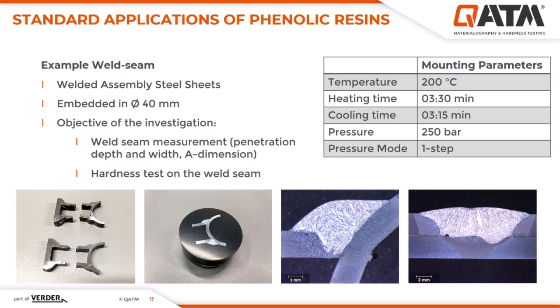The sample was then ground in 2 steps using a metal bonded diamond grinding disc with a grit size of 54 micron and 10 micron. These diamond grinding discs, called Vega, achieve a very high removal rate and deliver excellent results in a very short grinding time. This was followed by a 3 micron polish, and after etching with 3% nital solution, the microstructure could be analyzed and we had perfect results.